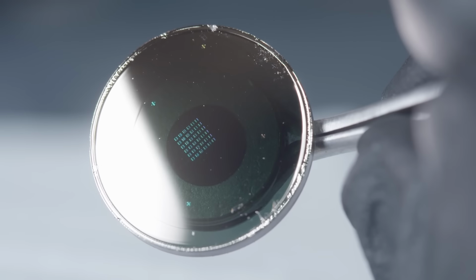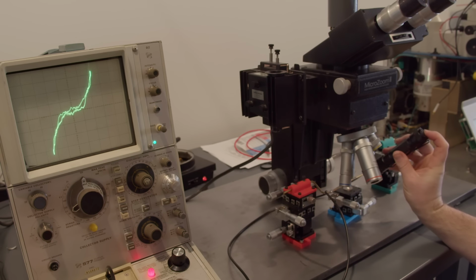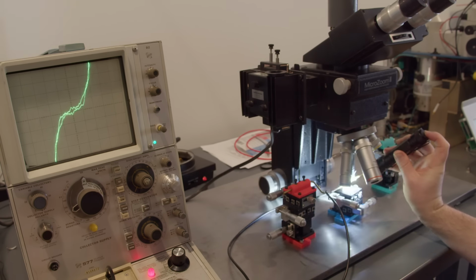Which means it's time to start over and rerun the whole procedure on our quartz wafers. Depositing copper, oxidizing in the furnace, patterning, developing, depositing aluminum, and finally the liftoff. And when we probe it, okay, so the curve isn't quite as impressive as before, but it's very clearly photosensitive.